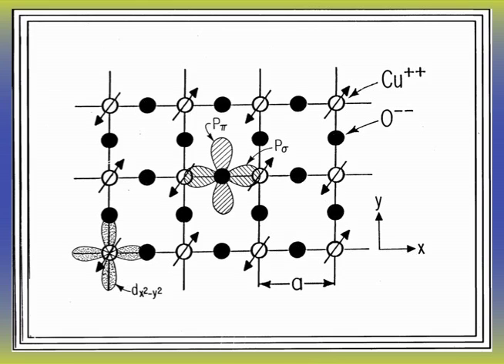But there's one extraordinary feature here, which in the brief time we have, I will not dwell on, which is that each of the copper atoms in the insulating state at least has a spin. But it was believed up until this discovery that magnetism and superconductivity were completely incompatible. And then we find that the highest temperature superconductors, rather than excluding magnetism entirely, seem to have magnetism present at the atomic level.